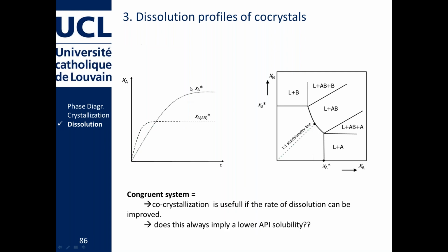So now you're going to say, why is this useful? Because this will only lead to co-crystals which have a lower solubility than the pure component. Yes, but I forgot to tell you one thing. In the beginning I said the solubility of caffeine does not alter with the amount of maleic acid. This starts from the idea that they don't interact in solution, which clearly they do if they're willing to go together in the same crystal structure.